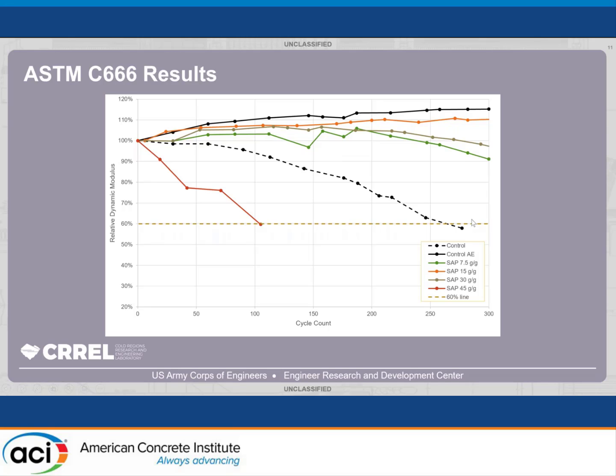Even though it wasn't air entrained, it had those freeze protection additives included in it, and so it lasted over 275 cycles, which is pretty strong. But all of our other SAP entrained mixes performed pretty well for this test, with our only one failing being the lowest dosed SAP. And as I said, the strength at 7, 28, and 90 days for that mixture didn't really gain very much over time either.